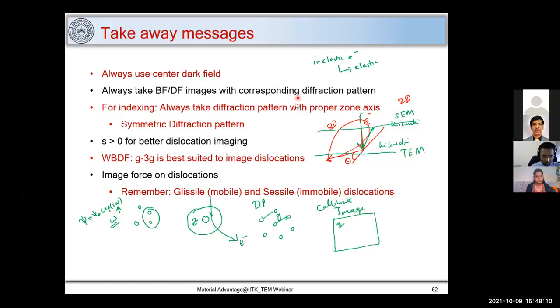As far as I know, you don't have to go more than 10 degrees in beta tilt, and you don't have to go more than 30 degrees in alpha tilt. If you can't image between these ranges, it is unlikely that you have dislocations you can image. Okay. And it depends on the goniometer also.